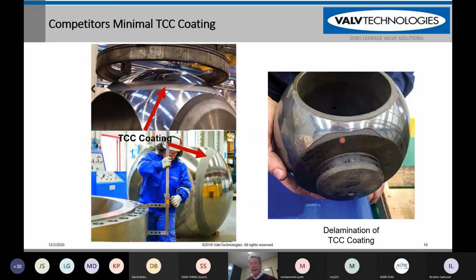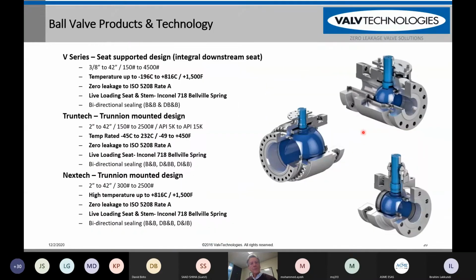Another issue that your valves can have is what's known as delamination. You can see here that the tungsten carbide looks very, very good, but it's delaminated around the seat and it's delaminated around the ball. So that valve will leak.